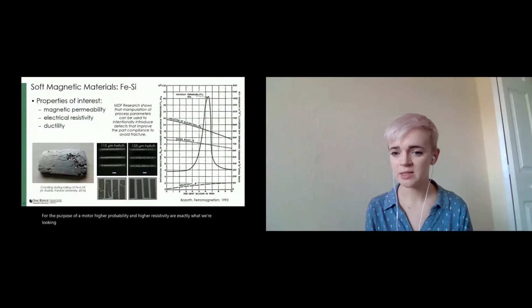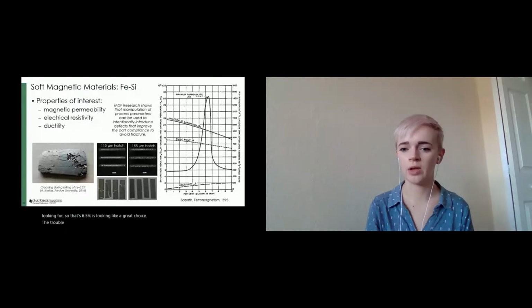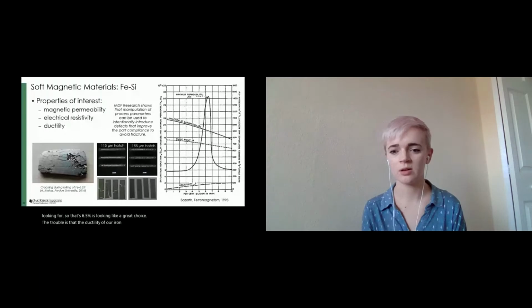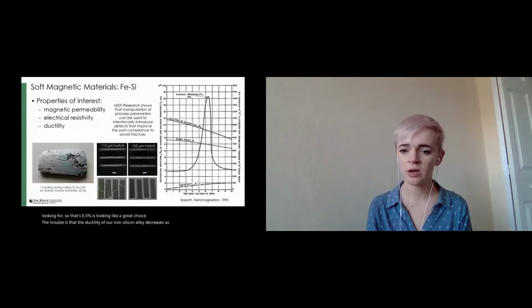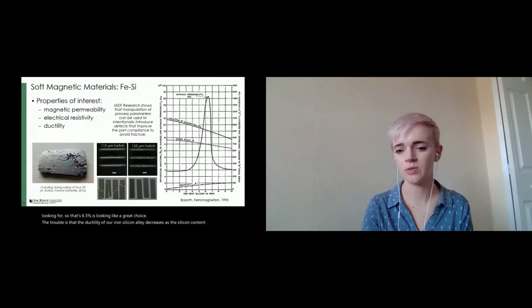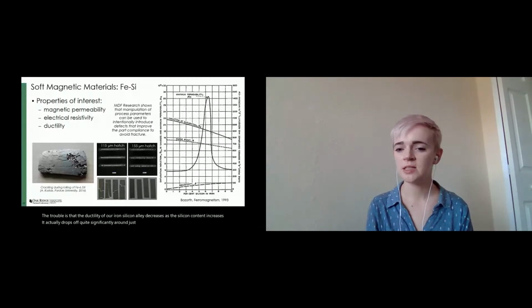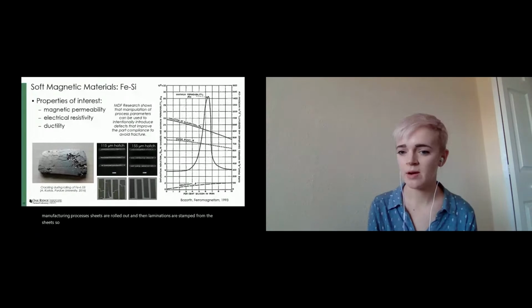The trouble is that the ductility of our iron silicon alloy decreases as the silicon content increases. It actually drops off quite significantly, around just over 3% silicon. In today's typical manufacturing processes, sheets are rolled out and then laminations are stamped from the sheets. So low ductility presents a big problem here, as you can see in this image on the bottom left.